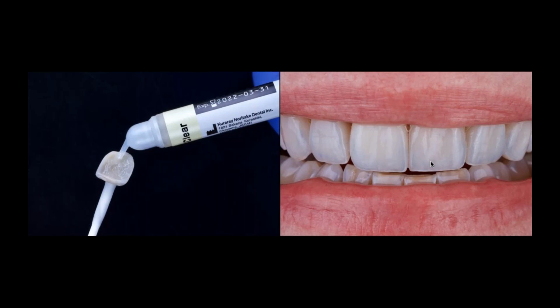You can etch it for 20 seconds. You can apply the conventional silane and do the full adhesive cementation. What I like is that it has a nice chromatic look. It's not gray, the final aspect. And here, what I always try to do is to use the clear try-in resin cement. This is from the Panavia V5, which is the cement that I like to use every day.